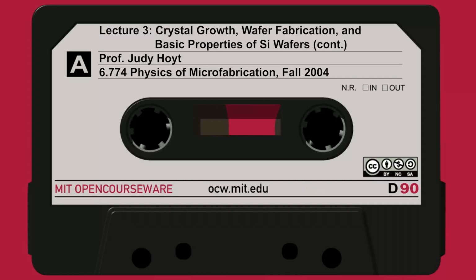The surface generation and recombination is very common. The crystal has a number of different ways to achieve different concentrations of vacancies and interstitials, even in equilibrium. And when we change the temperature of the crystal, the concentration of vacancies and the concentration of interstitials will change by the creation of either Frenkel pairs or atoms moving in and out of the surface and interstitials diffusing in.